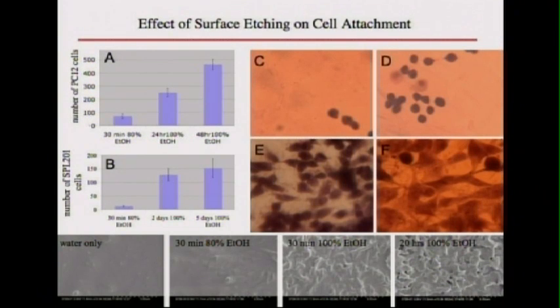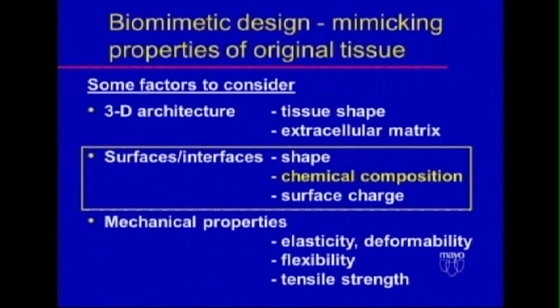We found a couple other things. If we etch the surface, as you can see, the two nerve lines we use, the PC12 and the SPL201, as we expose the scaffold to increases in both the concentration and the length of contact of alcohol, we get more and more roughness. The cells seem to like roughness, and more of them attach when it's rough.